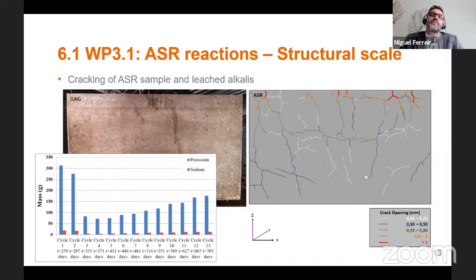So we made some calculations, and we estimated that approximately 9.5% of the initial amount of alkalis leached. So this is something that is not negligible. And if we think about the kind of tests that we do in the lab with the core samples that are conserved at high relative humidity, but not immersed, and very little leaching occurring there, we can already see here another factor that might be influencing the way the results in the lab don't necessarily simulate results in real structures. And then, of course, this acceleration protocol itself might not be representative of all NPP concrete structures as well.